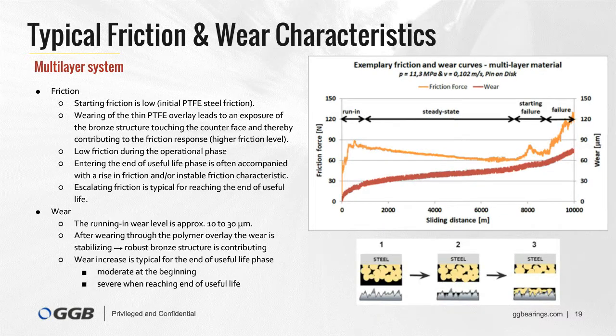This slide shows the typical outcomes in friction and wear for a multi-layer material. Normally these materials show typical friction and wear phases during their wear life. They often start with a low friction level, attributed to an initial friction with high content of PTFE. The duration of this transient phase strongly varies from experiment to experiment. Both the variation in polymer overlay thickness and variances in counterface topography are two dominating factors for this phase. After this short initial period, the friction characteristic changes.